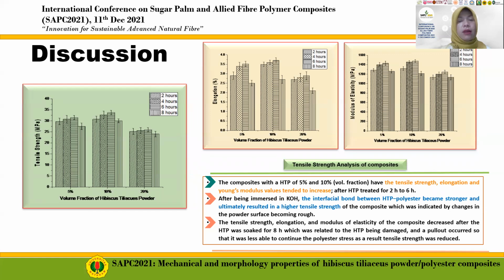The tensile strength, elongation, and modulus of elasticity of the composite decreased after the powder was soaked for 8 hours, which was related to the powder being damaged and a pullout occurred, so that it was less able to continue the polyester stress. As a result, tensile strength was reduced.